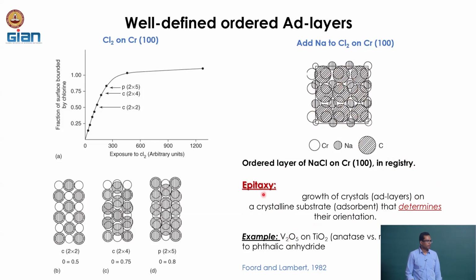V2O5 on titania. Now, titania can have different crystal phases, and the typical ones are anatase and rutile. When V2O5 grows on anatase versus rutile, in one case we see the epitaxy formation, whereas in the other case we do not see it. And when that is subjected to a reaction, for example, orthoxylene to phthalic anhydride, we see one of these phases is more active as compared to the other phase of titania.